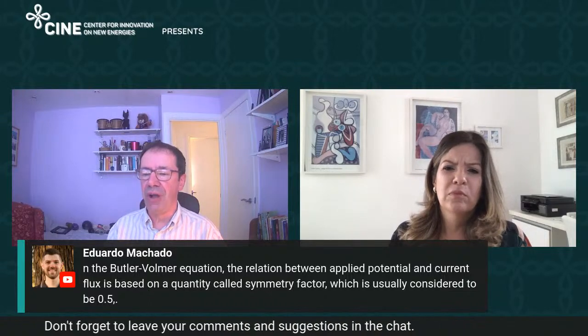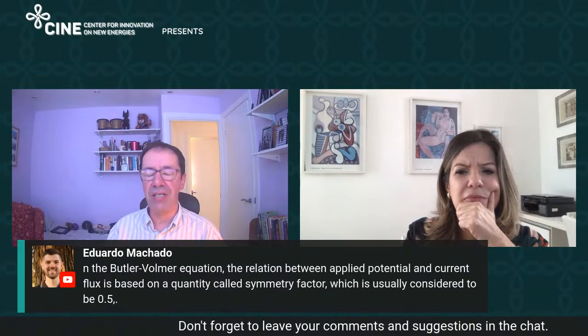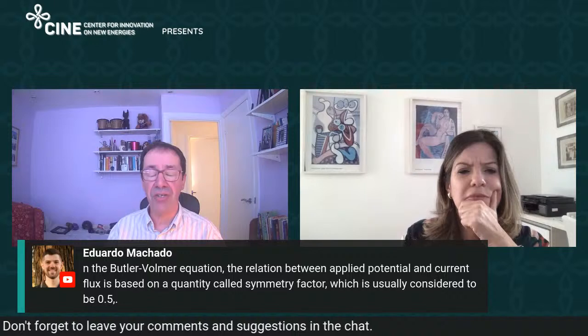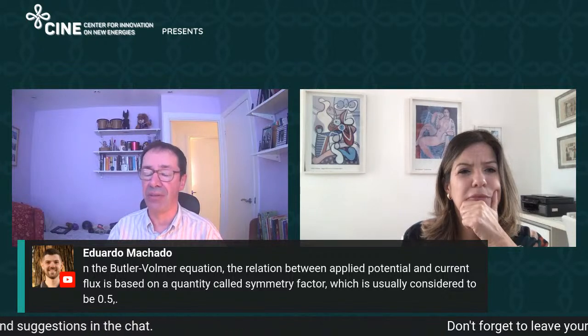So this is about how to analyze the Butler-Volmer behavior and the symmetry factor, so the whole idea behind that analysis. There's my picture on that. The idea is that as you apply a potential, you reduce the activation barrier to a reaction. The scaling factor or symmetry factor, which you refer to, refers to how much potential you have to apply to reduce the activation barrier by a certain amount. A symmetry factor of 1/2 means you have to apply 100 millivolts to reduce the barrier by 50 millivolts.